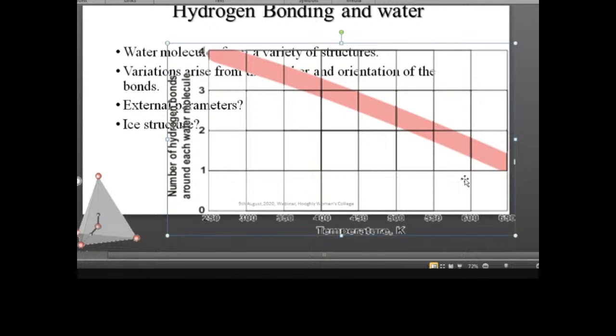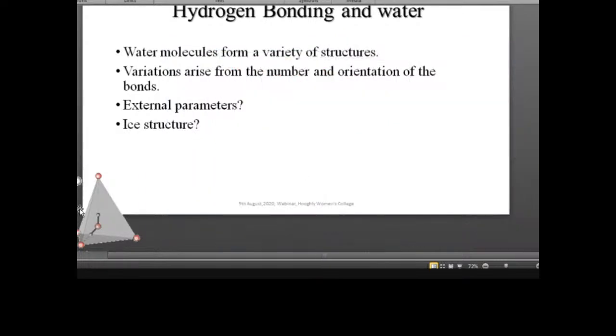And you can find that even if you go to 650 degree Kelvin, that means it is not so low a temperature, roughly about 400 degree centigrade, you are moving much above the boiling point. So even at 400 degree centigrade, in the vapor state, not all the water molecules are separated out, and they actually have at least one bond with them. So at least two water molecules are there.